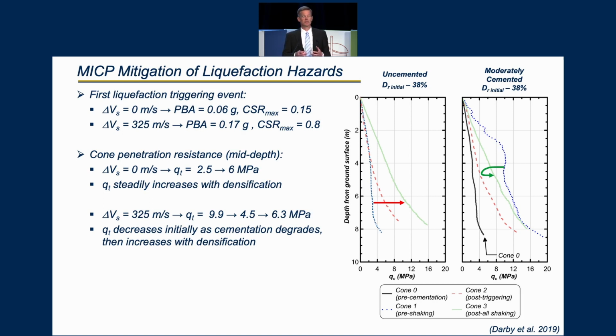Following liquefaction, that cementation degraded somewhat, and the cone tip tracked that. It decreased a little bit initially, but then with further shaking, even as the cementation is being damaged to a certain extent, it also starts to densify, and as a result, the cone tip resistance goes up.